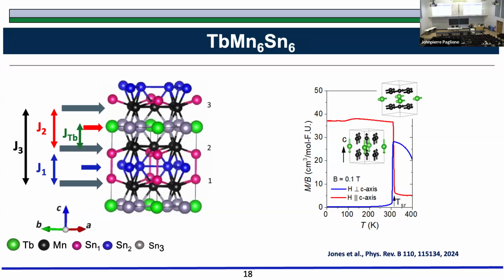This is another compound. Here, now this is terbium. Now we replaced yttrium with terbium. And then what we get here is that now we have this J1, J2, J3, all the magnetic interactions. On top of that, terbium also is a magnetic element. Now there is interaction between terbium and manganese layers also, right? So there is another J here. So the J effective becomes different here.